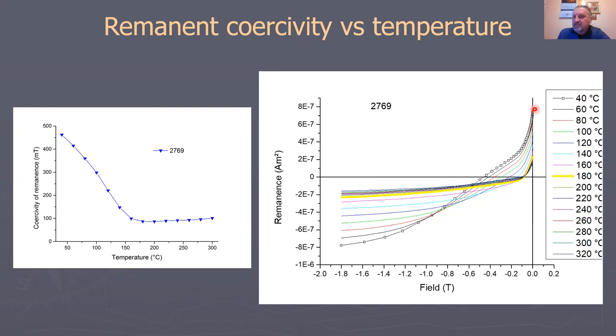At room temperature and slightly above, the zero magnetization axis is crossed in the hard phase, but starting at probably 180, which is shown there as the bold yellow curve, the crossing occurs already in the soft phase, and so the curves above 180 are almost indistinguishable.